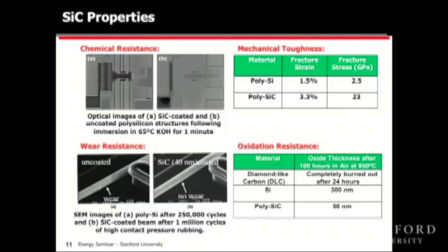And its oxidation resistance is very superior to diamond. After exposing diamond-like carbon films to 100 hours in air at 850 degrees C, the diamond-like films completely disappear after 24 hours. The silicon films generate an oxide layer of around 300 nanometers. The silicon carbide films generate a very, very thin oxide layer of only 50 nanometers that terminates after a particular point. So again, this is just highlighting the superior chemical, mechanical, and wear resistance of silicon carbide.